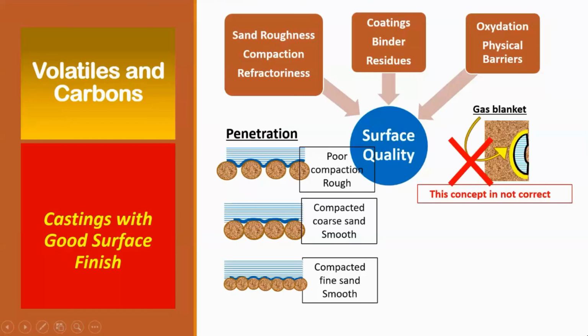But this concept is not correct because in general, the gas that is going to develop will always have a tendency to move upwards. So when you're pouring a heavier casting, the metal which is first entering the mold will try to settle at the bottom of the mold and then start slowly rising. So with the weight of the metal, the gases don't have a chance to remain there. They won't remain, they will just escape out.